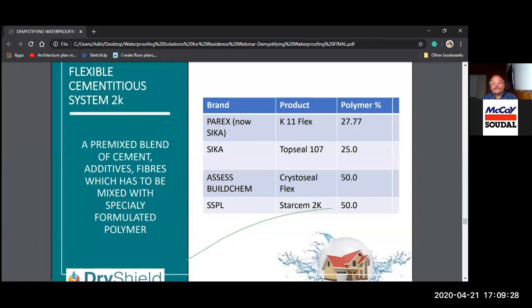ASSESS BUILDCHEM, Cristoseal Flex, is an amazing, highly flexible product. I have not tested it, but as per the company's TDS and test report, it has almost 150% elongation and 50% polymer. Again, Star Specialty Polymers, Star Sam 2K, is also 50%. Among these 4 products, apart from polymer content, another major difference is that ASSESS BUILDCHEM's Cristoseal Flex has a crystalline admixture added. So this product gives dual benefits. It's crystalline and also a two-component flexible system. It gives you the best of both technologies.